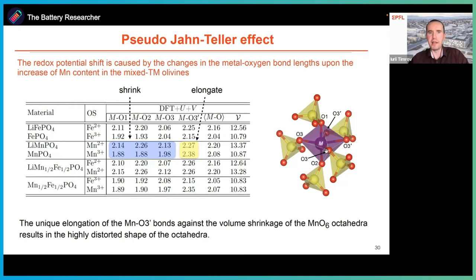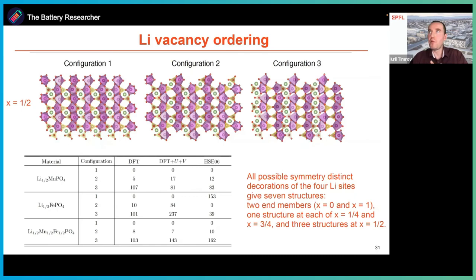Let us talk a little bit more about lithium vacancy ordering. So since we study different lithium concentrations, one has to pay attention to different possible configurations of lithium. All cases except x equal to 1/2 are quite unique. So there is one possibility, one configuration. But at x equals 1/2, there are three possibilities for how we can arrange lithium. And they are shown here.